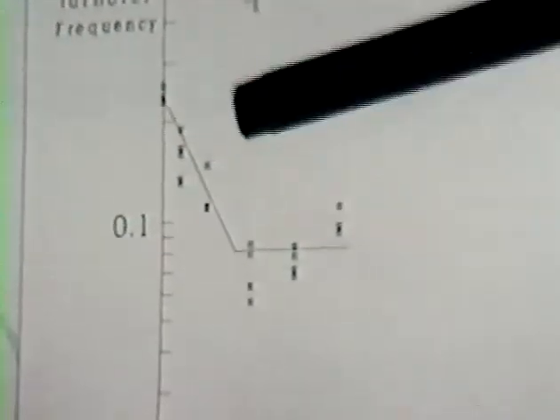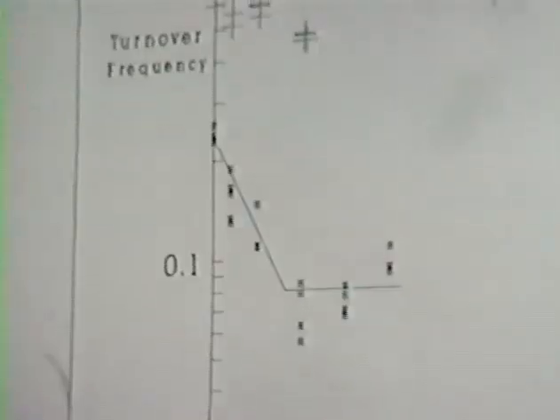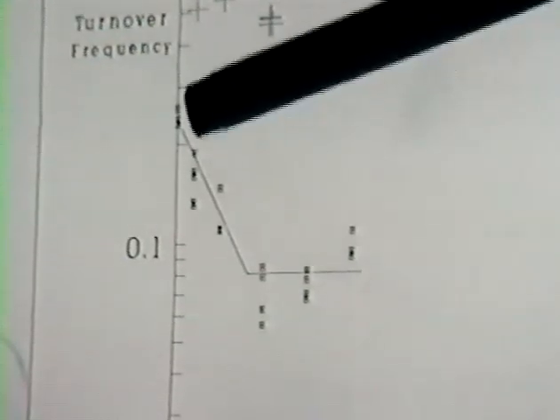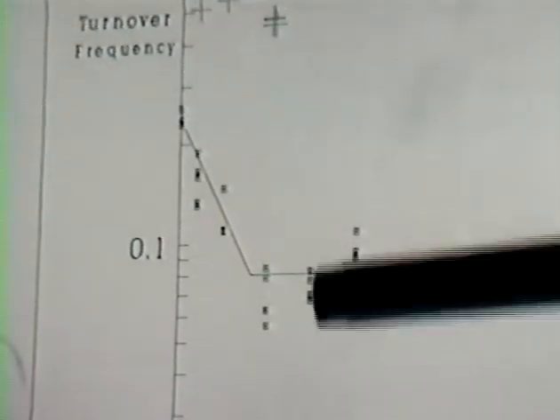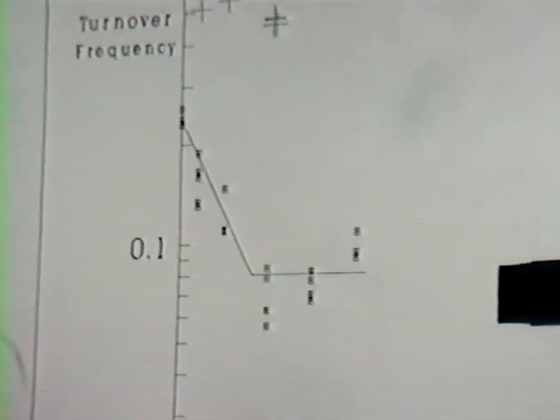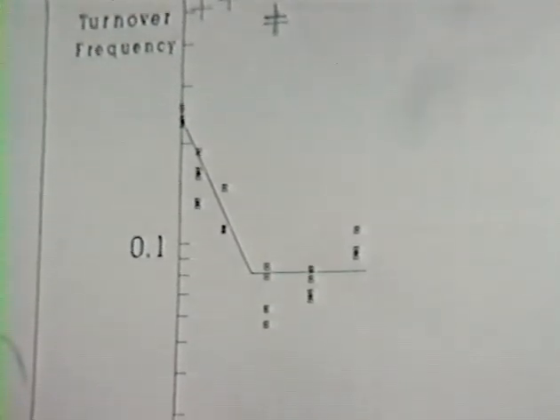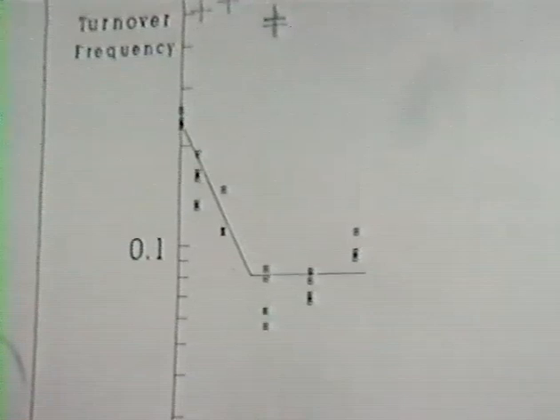What we think is happening: at low temperature, this initial decrease in activity is due to the loss of edge and corner sites for ruthenium. In the simulations, 10% is where we lose all those edge and corner sites. It appears to be a structure-sensitive reaction in the sense that edges and corners have different activity than the basal planes. Once we fill those edges and corners, the turnover frequency looks like it does on a single crystal — we're just blocking sites, not making small ruthenium ensembles. There's no geometric effect.